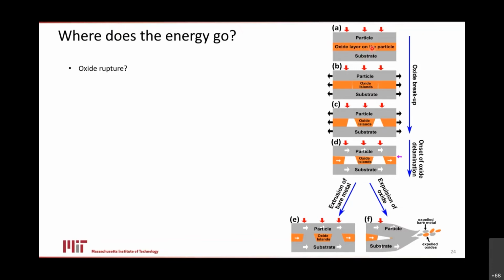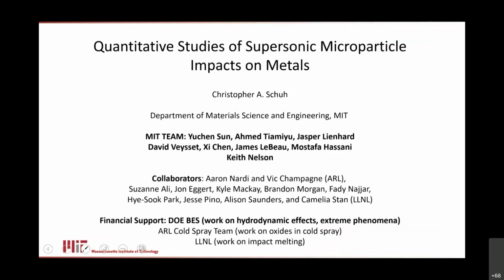So we know that we need enough deformation somehow to fracture that oxide layer, produce individual islands, squirt metal through and get contact between particle and substrate. And maybe that jetting process at the edge helps us squirt oxides out and form clean contacts. But oxide is really important to the phenomenon of bonding. So let's talk a little bit about oxides.